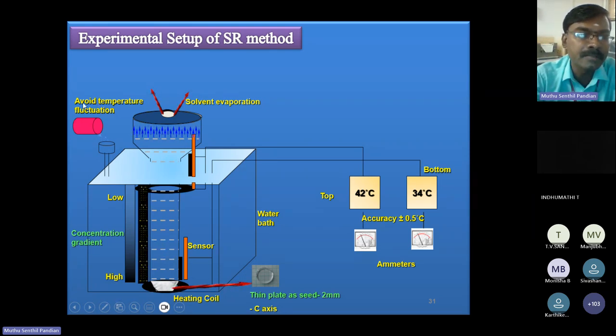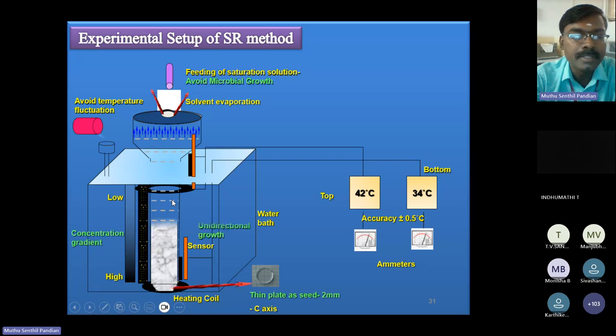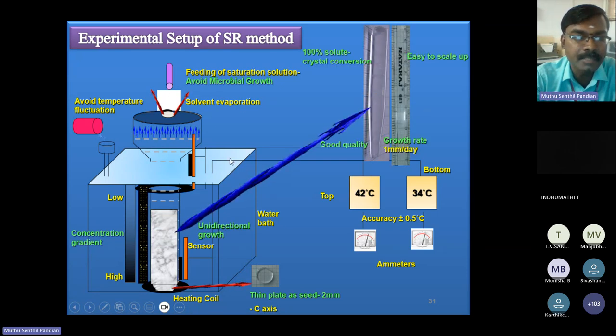To avoid temperature fluctuation from daily variation, water is frequently added inside this water bath. So we have to maintain a uniform water level, otherwise we cannot maintain the uniform temperature at the top and bottom portions. To avoid fungus growth, freshly prepared saturated solution is frequently added inside this SR glass ampoule. So this is the complete experimental setup of this SR method.